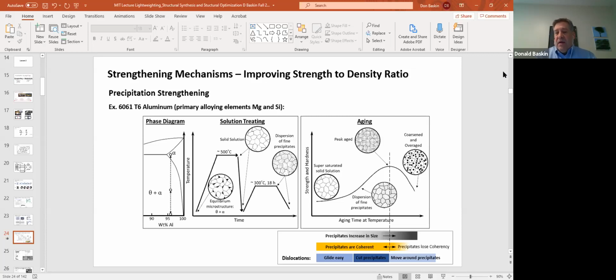So if you continue to heat this material, say at 300 degrees Celsius, these little precipitates will grow and grow and grow. And at that point, they lose coherency with the material around them. That is, the atomic planes don't line up. Then when a dislocation comes its way, it's very easy for the line of dislocation to just move around this precipitate. The material begins to lose strength at that point.